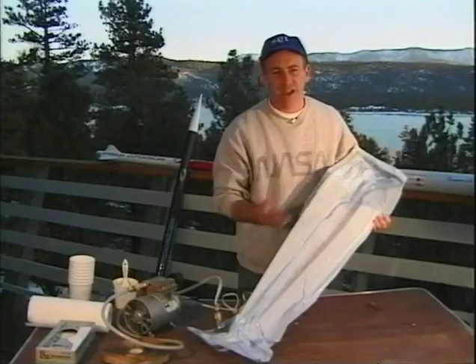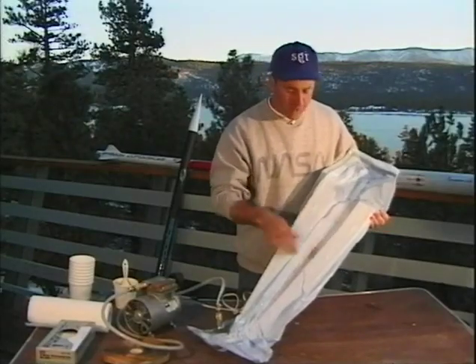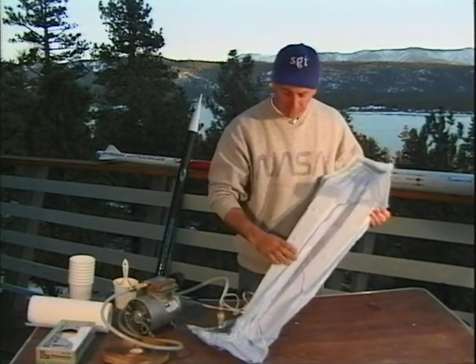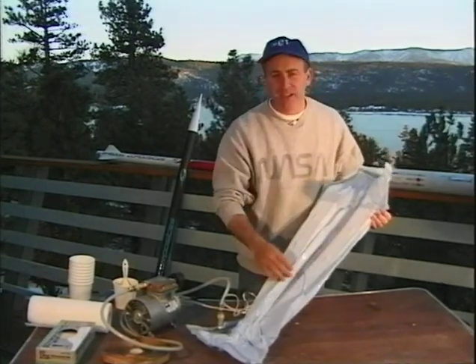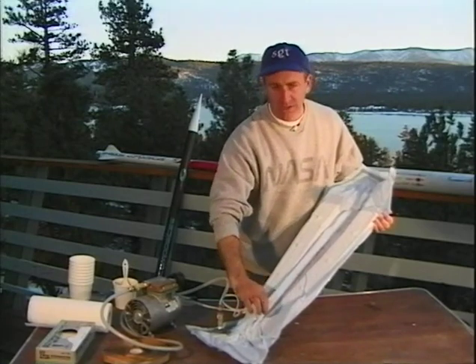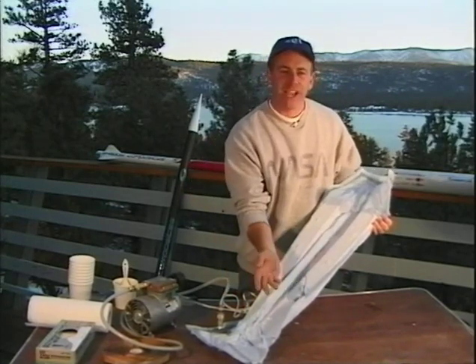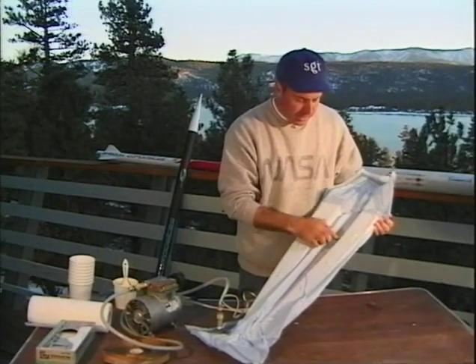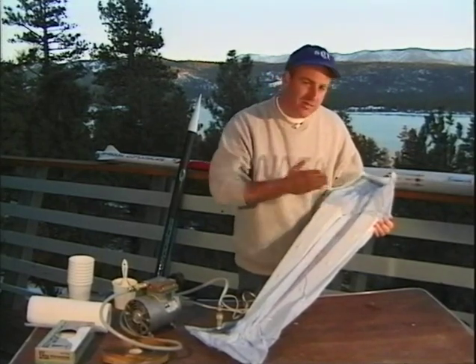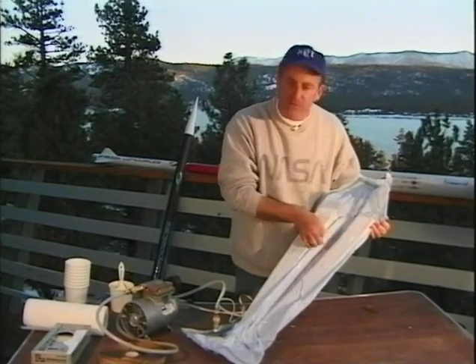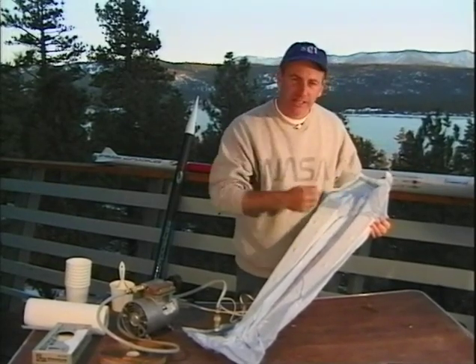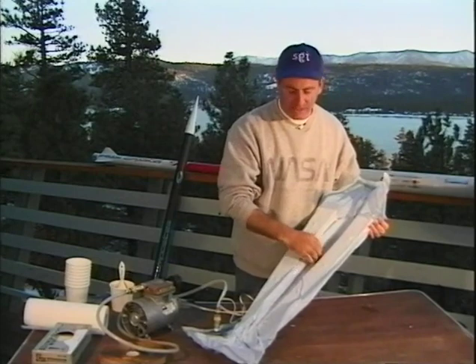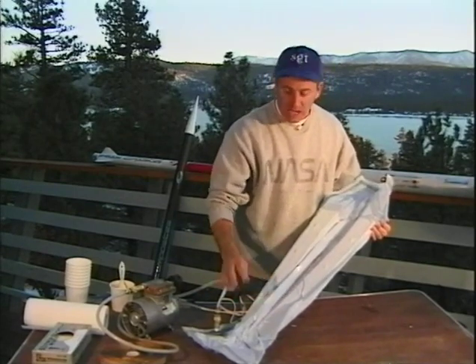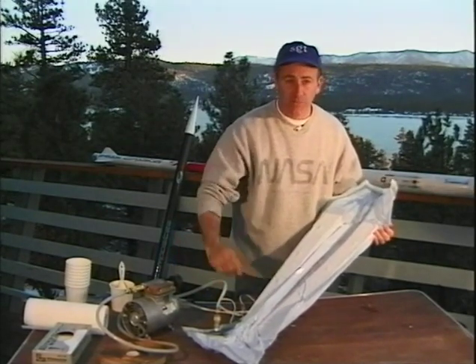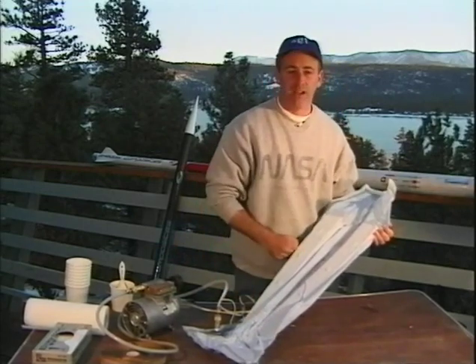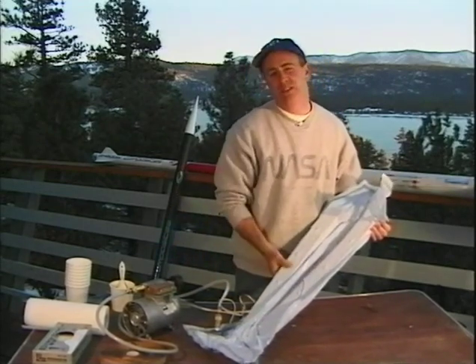This is what vacuum bagging is made for. Parts with a lot of contour. Using this technique and making sure you've got folds to get enough bagging material down into there. Also, if there's a shoulder area, or somewhere you want to really drive that stuff down in, put a fold over it. That will enable the bag material to really compress it down in. So be careful where your folds are. If you don't have your folds just right, let the vacuum off, kind of readjust them and suck it down again. But now this part would go into an oven for cure.